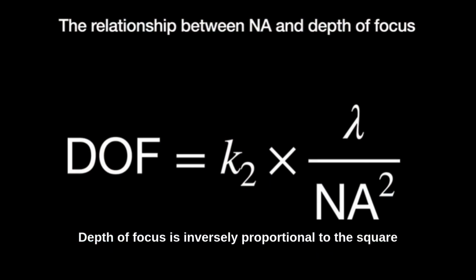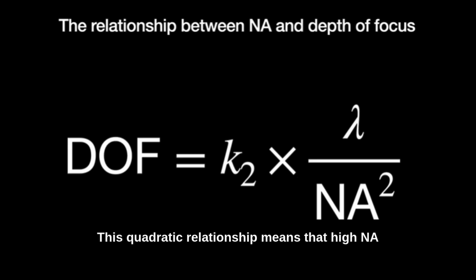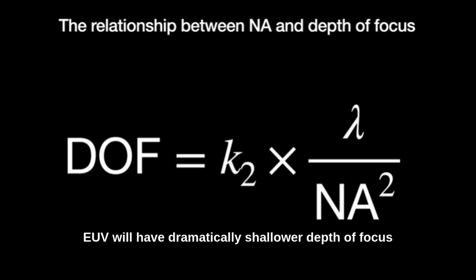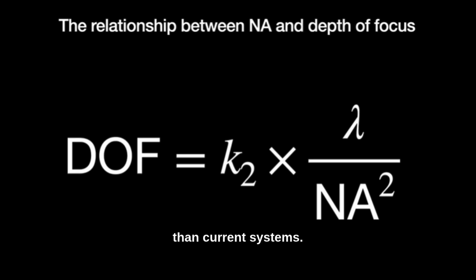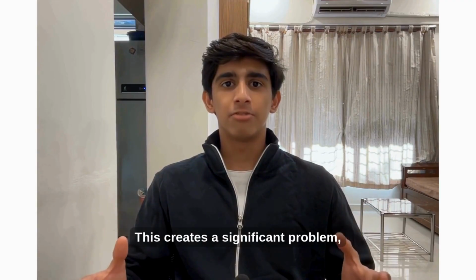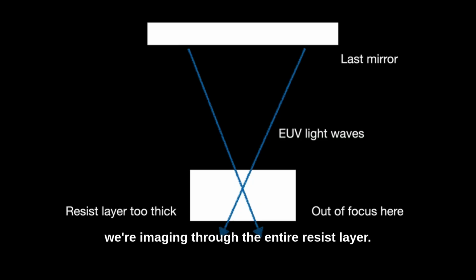The relationship is brutal. Depth of focus is inversely proportional to the square of the numerical aperture. So if you double the NA, your depth of focus becomes 1/4 as deep. This quadratic relationship means that high NA EUV will have dramatically shallower depth of focus than current systems. This creates a significant problem, because when we image the wafer, we're imaging through the entire resist layer.